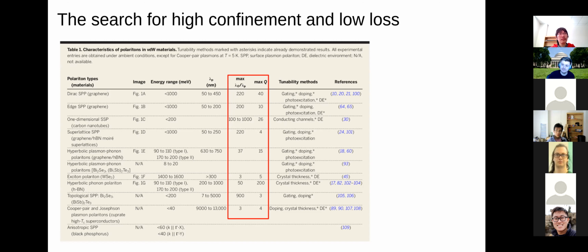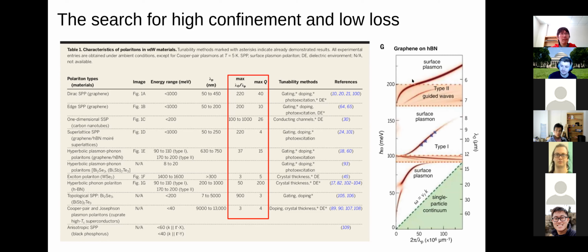The details of loss will depend on the microscopic mechanisms that are present within that material, but people are very interested due to the subwavelength nature, and also the ability to create new dispersions that are engineered. So this is an example of a dispersion relation of some kind of sandwich made with graphene and hexagonal boron nitride. The graphene has a plasmonic type behavior, and then the boron nitride has a phonon polariton type resonance. And they're able to overlap these in frequency ranges to get a rich variety of both plasmon, phonon, and hybridized modes.